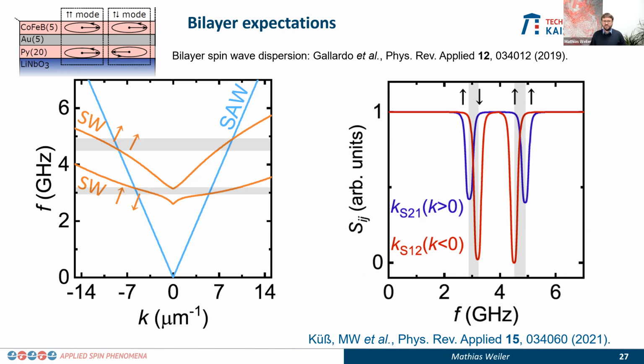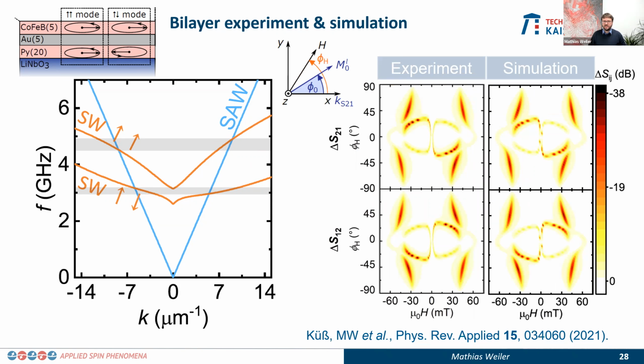Now that means what we would expect when we let the system interact with the reciprocal dispersion of the surface acoustic wave. We should get basically as a function of frequency these 4 different absorption peaks, right, corresponding to the individual crossing points that you get here, right? And you get the 4 different ones because it now depends on the direction of propagation of the acoustic wave. So we can again do that in experiment, and yes, indeed, we do observe for given orientation of the external magnetic field, right, you observe this 1, 2, 3, 4 interaction points. Okay.